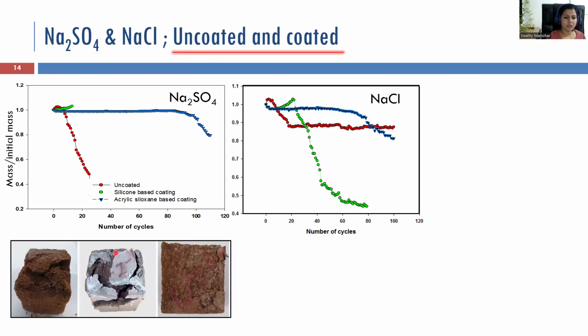Probably it would be acting as a complete sealant over the samples, which would create stresses inside the material and would crack up, open up. But when we are having acrylic siloxane based coating, which has a tendency also to form cracks during the exposure period, it would help in releasing the stresses out.